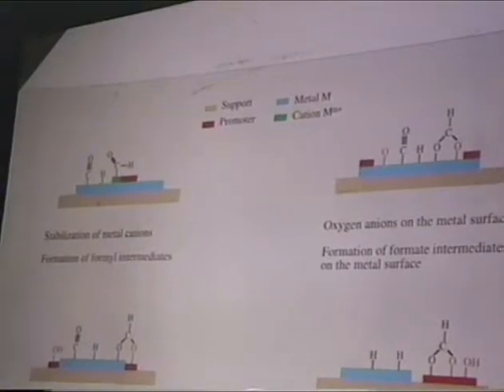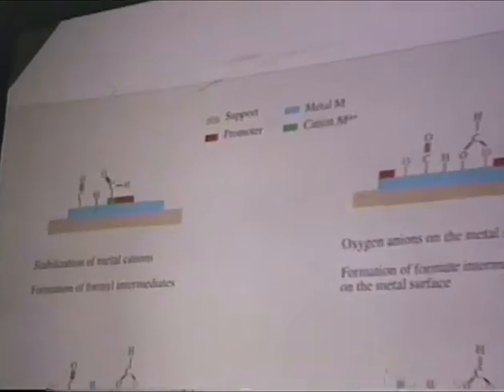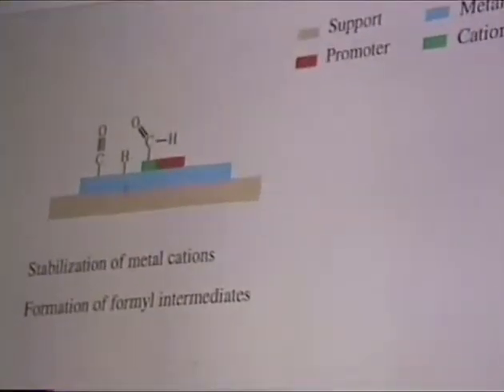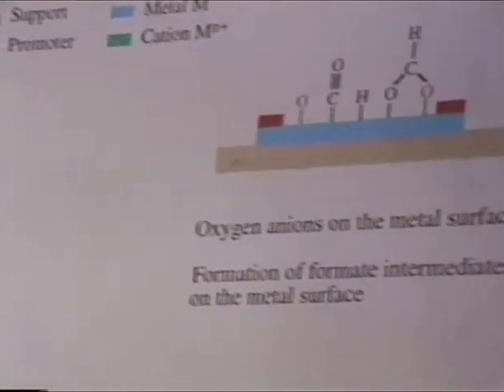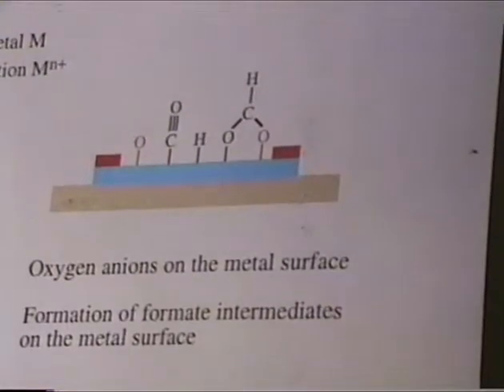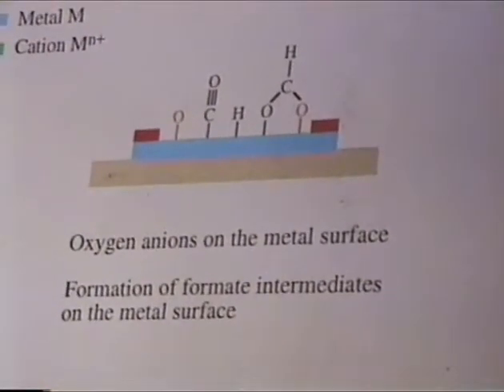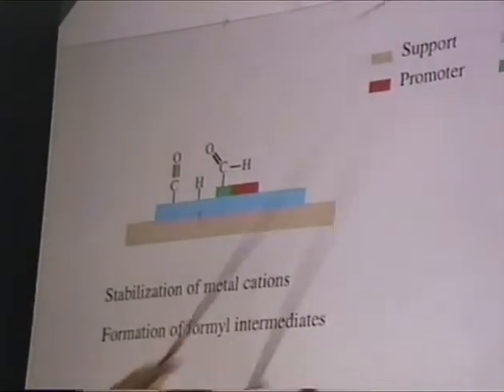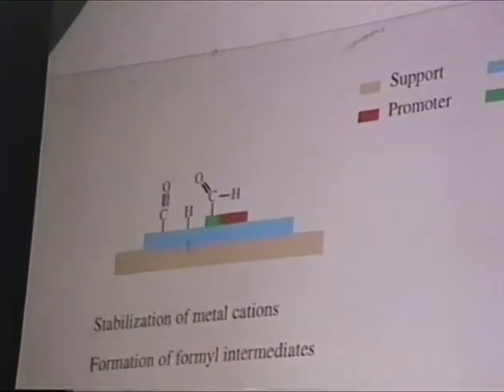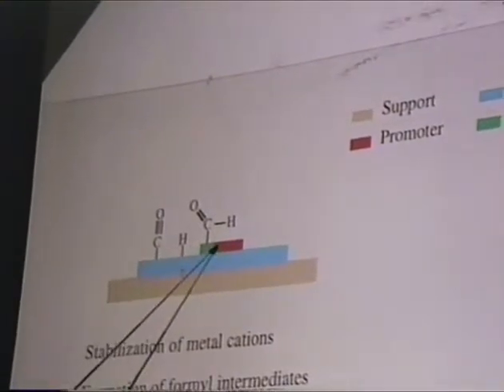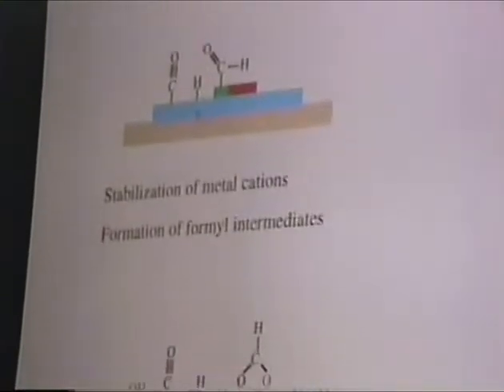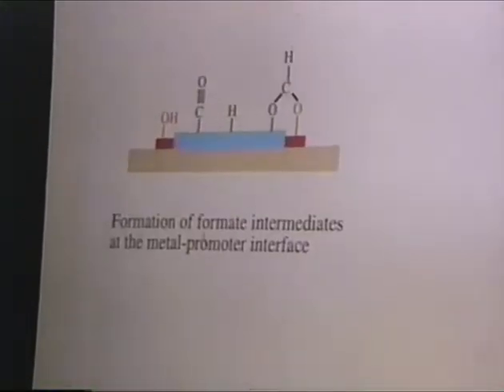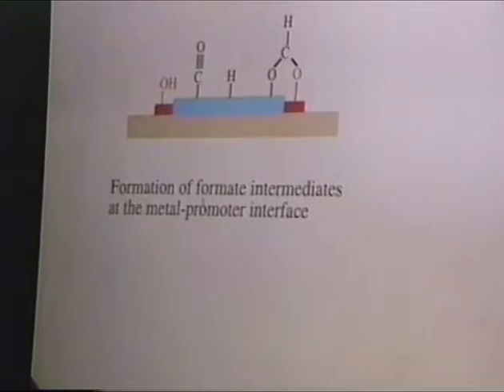Now, one which Professor Ponec favors quite heavily, and it's unfortunate that he is not here, I would have enjoyed a good fight with him, is the formyl intermediate. And his suggestion is that formyl is made on a cation. So if the red one were palladium, then he assumes that this is palladium plus, stabilized by an oxygen from the promoter, and that's then doing the job, and that goes through the formyl.